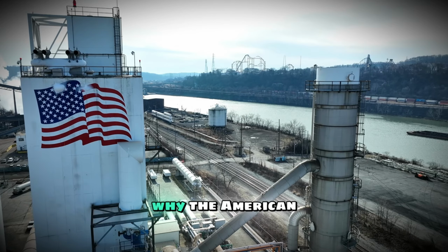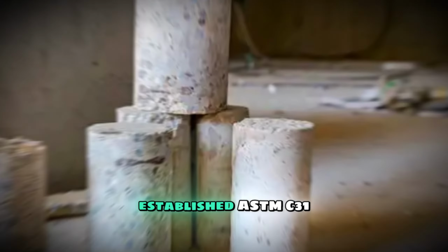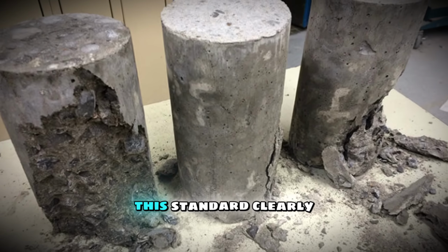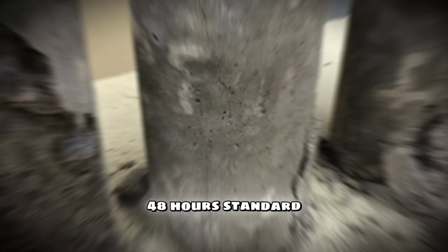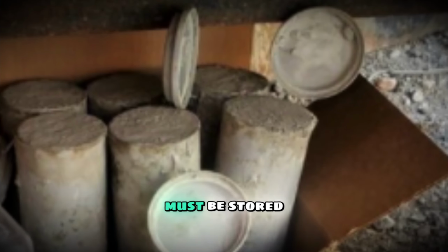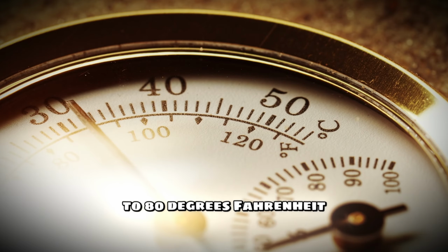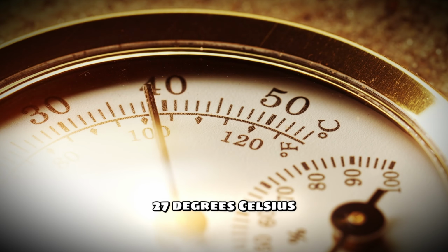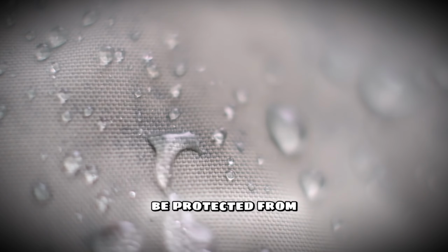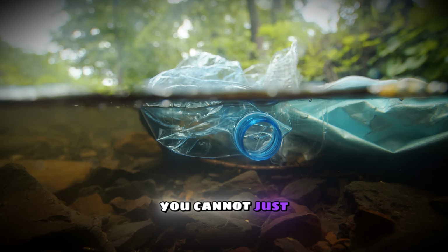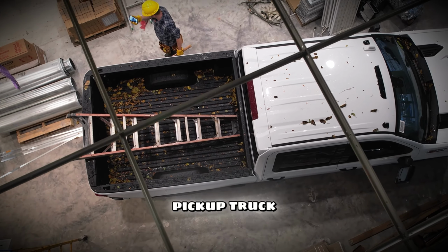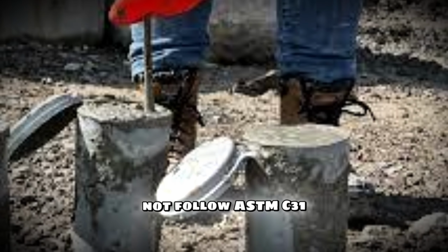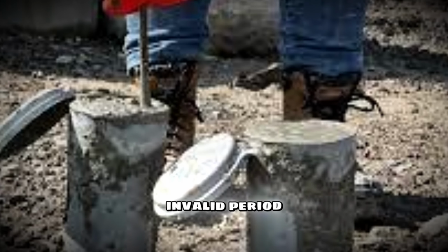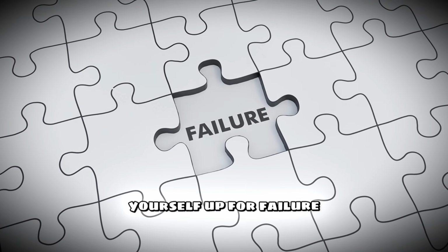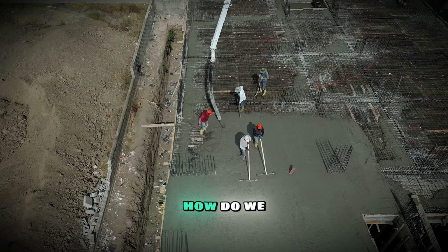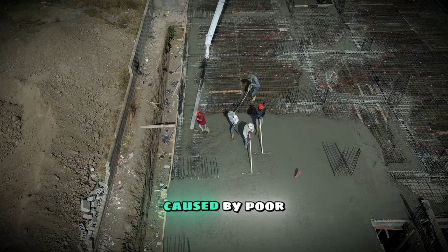This is exactly why the American Society for Testing and Materials established ASTM C31. This standard clearly dictates that for the first 48 hours, standard concrete test cylinders must be stored in a temperature range of 60 to 80 degrees Fahrenheit, or 16 to 27 degrees Celsius. Furthermore, they must be protected from moisture loss. You cannot just leave them under a piece of plastic or in the back of a pickup truck. If you do not follow ASTM C31, your tests are invalid, period. You are setting yourself up for failure. So how do we fix this? How do we completely eliminate bad breaks caused by poor field curing?